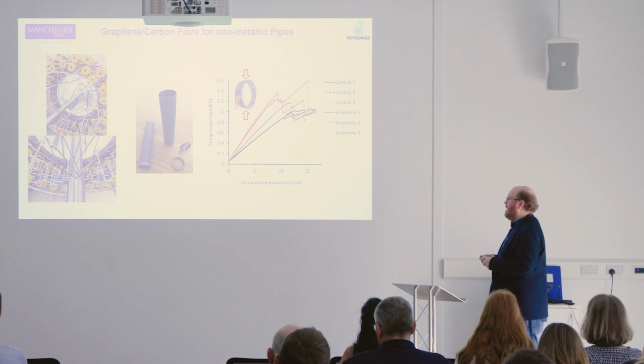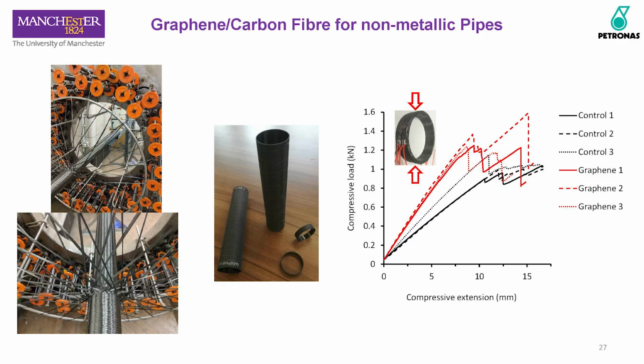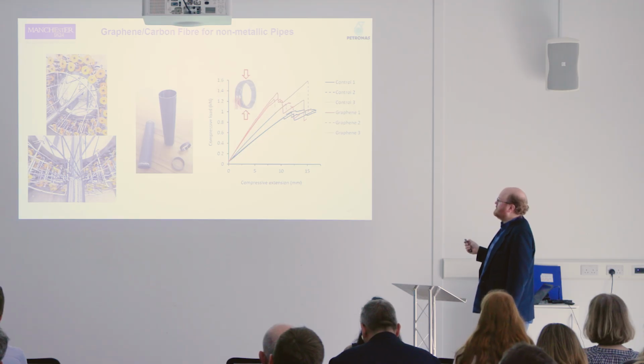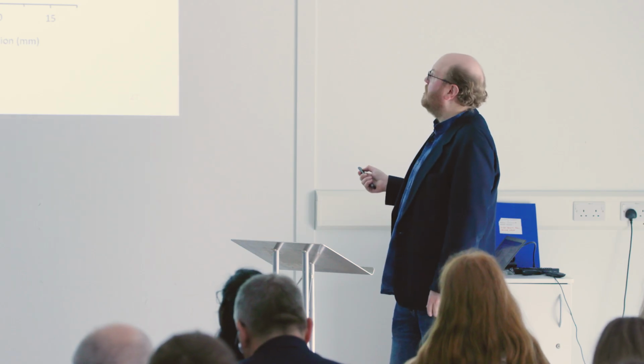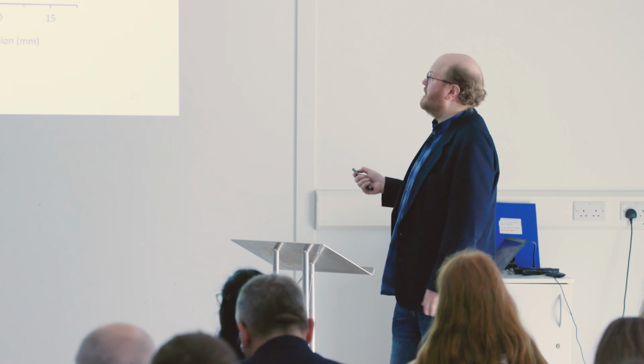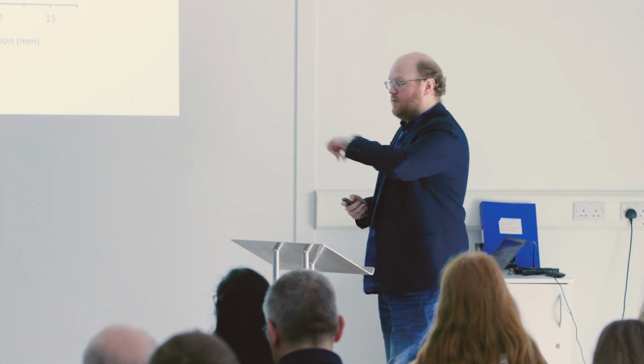This can also be scaled into different kinds of geometries, it's not always just flat coupons. This is some work we're doing here on braided carbon fiber, which is used, say, for pipelines or for making gas cylinders, or it can also be used for wind turbine blades or things like this. So we have these robotic winders, which we can use to coat these carbon fibers in graphene. And again, in terms of compressive strength, compared to the control, the modulus and the strength basically go up quite significantly by having graphene integrated into it. So we're getting this synergistic improvement: at a very low loading of graphene, less than 1% usually, we can get a big improvement in mechanical properties over just carbon fiber or just glass fiber, which is quite impressive.